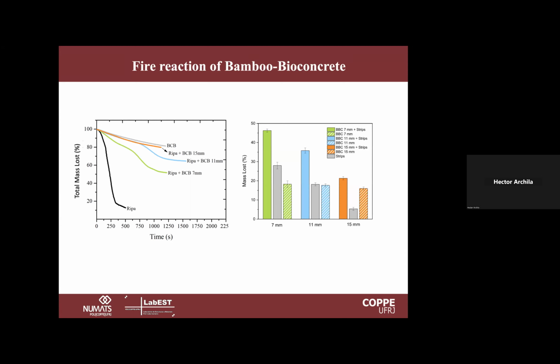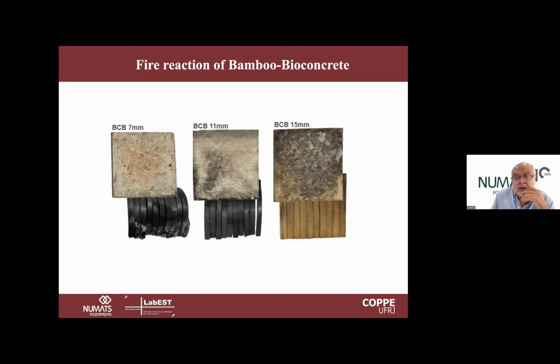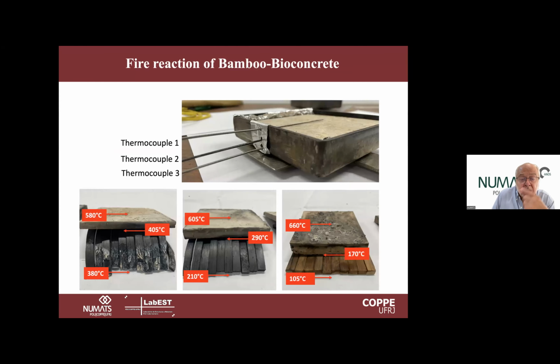So this shows the difference between the bamboo and the strip itself, and then it shows a picture here. When we have the 15 millimeters, the bamboo remains very much the same. Then we put thermocouples to see the temperature close here, and we see that when we have 15 millimeters, the temperature that reaches the bamboo is between 105 and 170. We saw already that this is enough to keep the properties of the material.